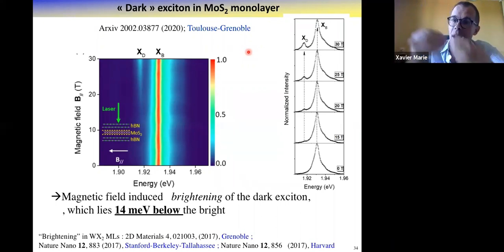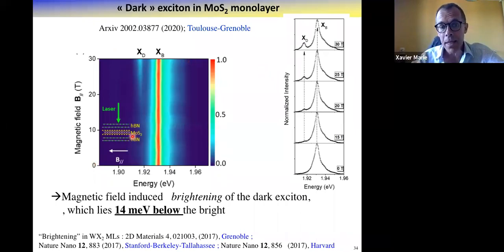If you mix with a bright state, you will give to the dark state some oscillator strength, and hopefully you will start to observe it in an optical spectrum. And indeed, we did this by increasing the in-plane magnetic field up to 30 Tesla. And you have here the magnetic field as a function of energy. The main line is the neutral exciton, X bright here. But you see, above 20 Tesla, you clearly see a new line which appears in this spectra. At zero field, you don't have it. And then it rises, and it corresponds to the spin forbidden dark exciton with a very low oscillator strength. And so we do believe that now we know where the dark exciton is in MoS2. It's 14 millielectron volts below the bright one. This mixing between bright and dark was already performed by many groups on W-based monolayers previously.